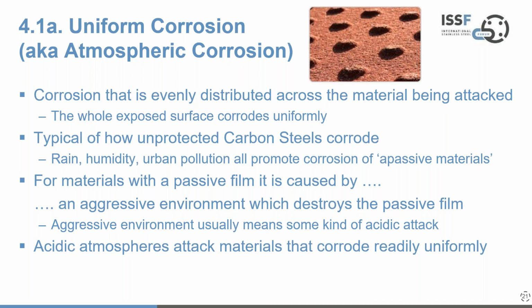And this is simply defined as corrosion that is evenly distributed across the material surface being attacked. So the whole exposed surface corrodes pretty much uniformly. And this is very typical of how unprotected carbon steels corrode. And this will be caused by rain, humidity, urban pollution. All these features and mechanisms promote corrosion of what we would term non-passive materials. So materials without a passive film.